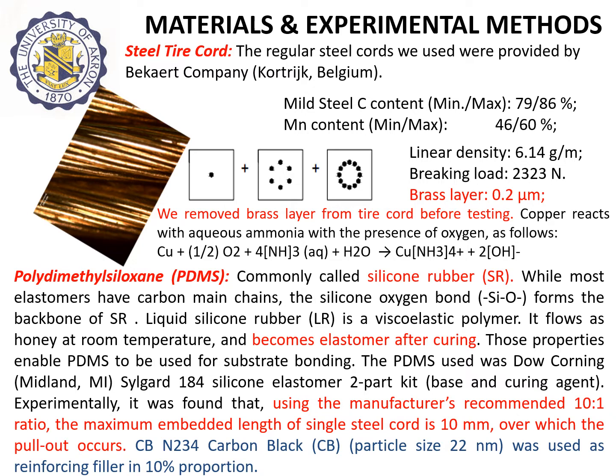We obtained this material from Dow Corning in two-parts kit containing base and the curing agent, where they were mixed 10:1 proportions, 10 base to 1 curing agent. We then embedded a single steel cord with an embedded length of 10 millimeters into this material that was cured. And we also added in the matrix carbon black, as I mentioned, carbon black of 22 nanometer size in 10% proportion for reinforcement purpose.